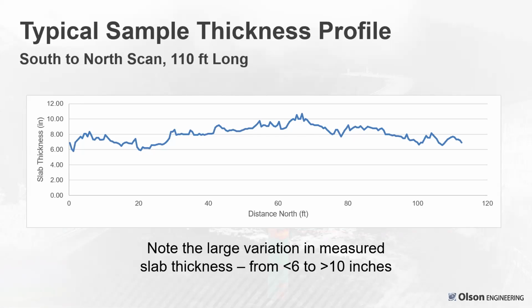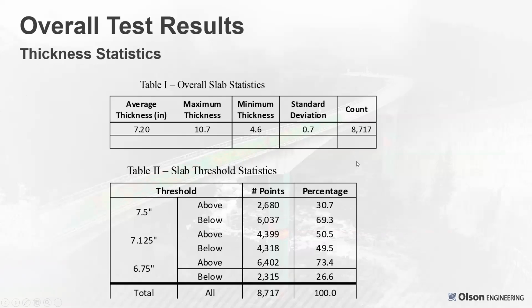So we took all of these scans and we did a statistical analysis on them, 8,700 plus valid points. And we're able to determine the percentage that were below and above certain thresholds that were relevant to this slab, to determine what percentage were below a certain threshold that would be considered of concern. And so the impact echo method worked quite well.